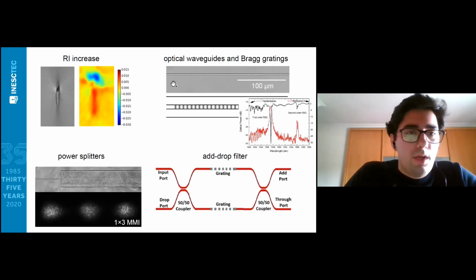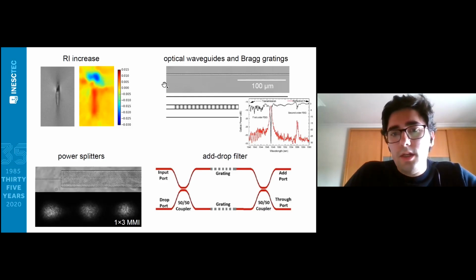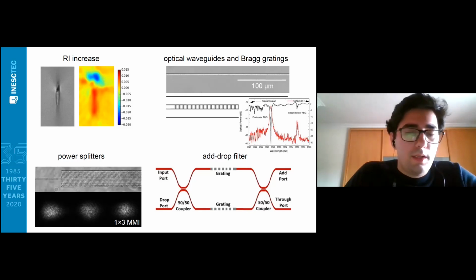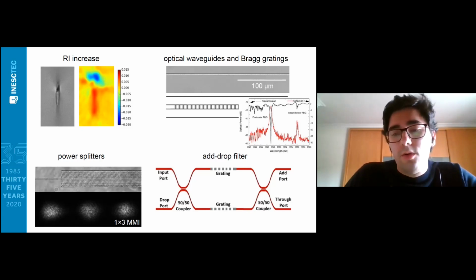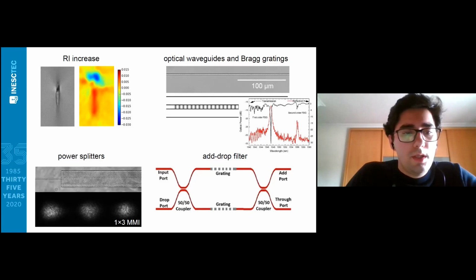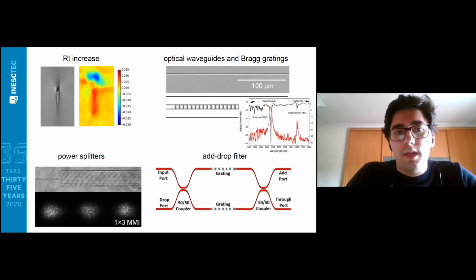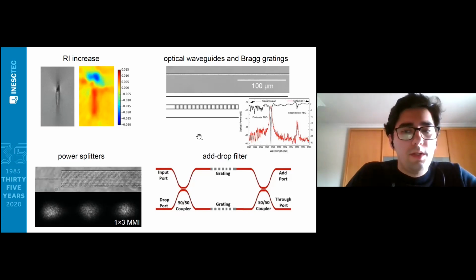Here you have an example of a straight waveguide, but we can also form bent waveguides. If we now modulate the laser pulse train, we can also fabricate Bragg gratings, as shown here, where we can have a reflection at a very narrow wavelength range. We have applied this technique to fused silica and to borosilicate glasses, and in the case of optical waveguides, we can fabricate them from the visible to the near infrared, with very low insertion losses. In the case of Bragg grating waveguides, we have also fabricated them in fused silica and in optical fibers. In optical fibers, we are also able to form long period gratings where light is coupled from the core to cladding modes of the fiber.